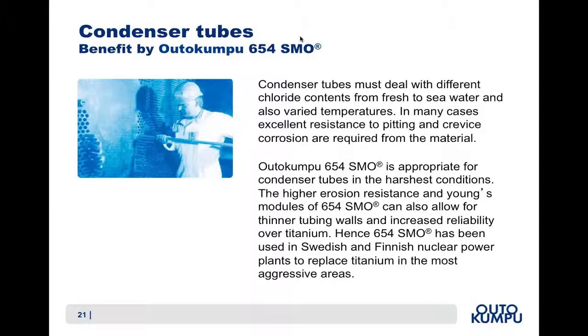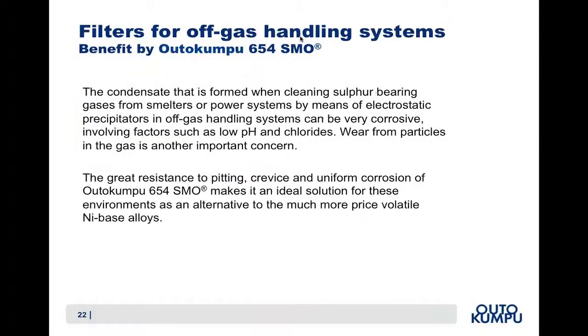Another application area for 654 SMO is condenser tubes, and it's been used in Swedish and Finnish nuclear power plants to replace titanium in the most aggressive areas. And due to the high corrosion resistance, it's ideally suited to applications with fresh or seawater across a wide range of temperatures. Yet another area where we expect to see increasing use of 654 SMO is in the filters for off-gas handling systems, where the condensate is formed when cleaning sulfur-bearing gases from smelters or power systems. And with a very high mechanical strength, it's also very resistant to the wear from particles carried in the gas, which is also very important.